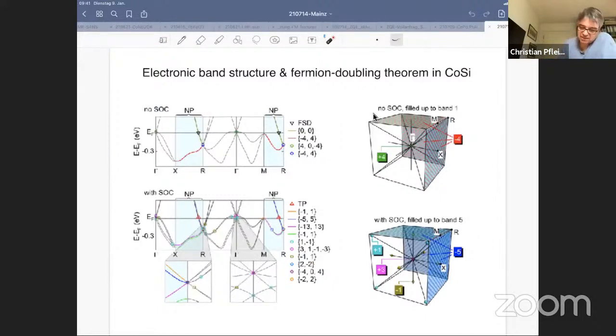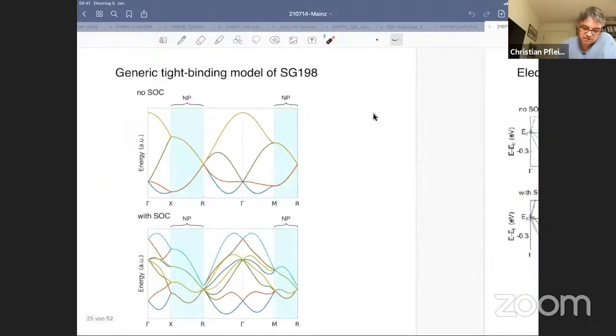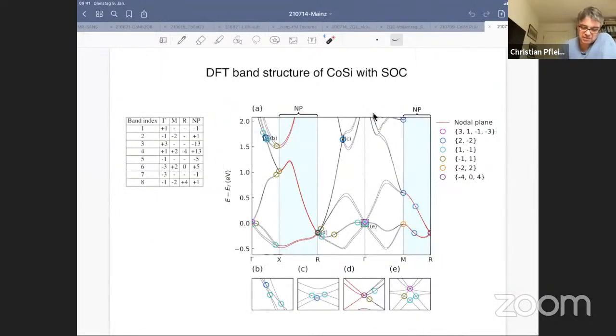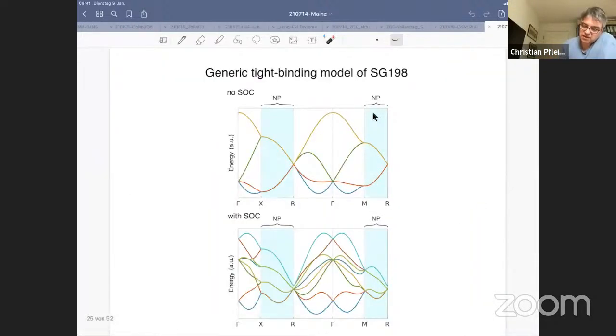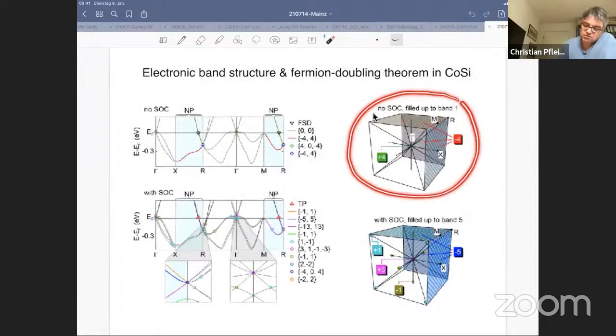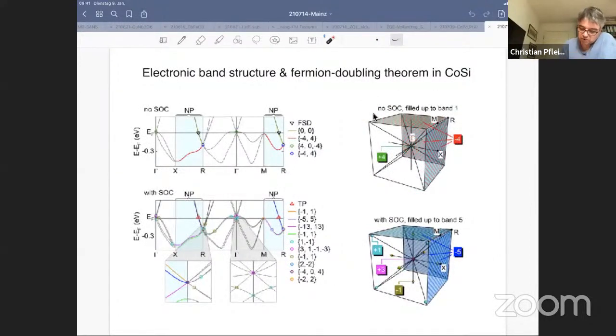One of the things you can see is that basically the crossing at the gamma point, right here, receives its charges. The way you analyze this is also summarized in this table here. You assume band filling up to a certain band, and then you can check what kinds of symmetry-enforced or accidental crossings are there, right? And then you have to do your sum, taking into account also the multiplicity of these points, taking different positions in the zone and so on. You find it always ends up to 0, right? So you're good. And so here you find that basically the nodal planes provide the charge for this gamma point without spin-orbit coupling.